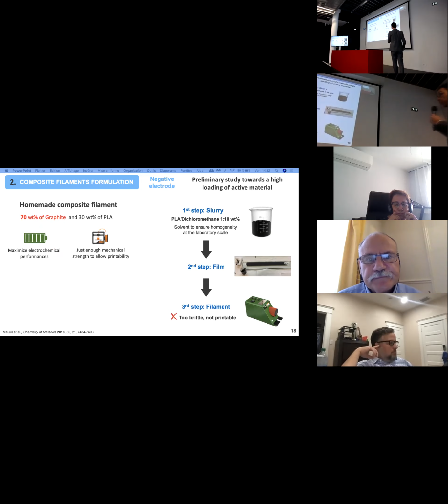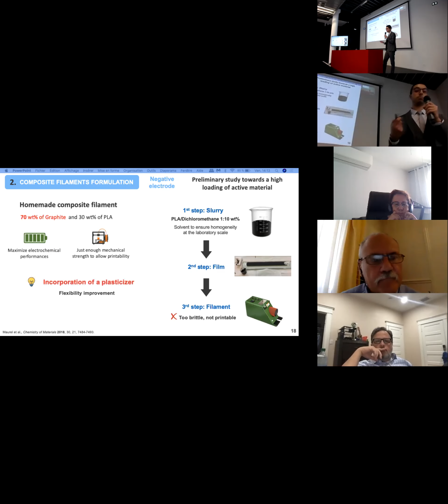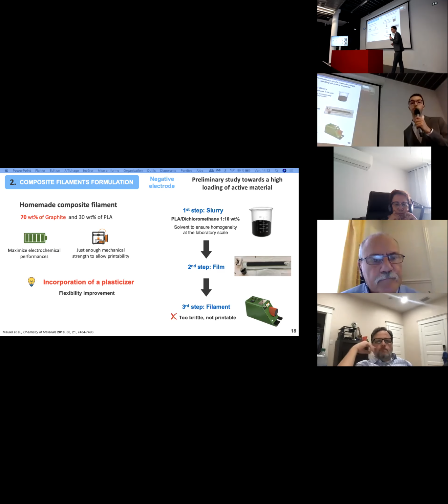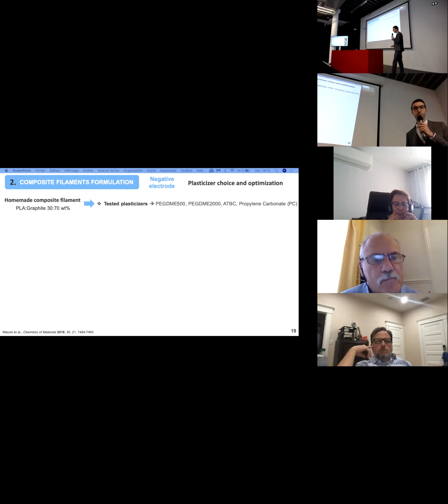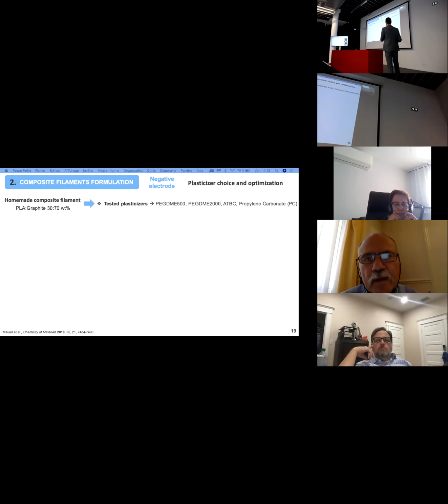It was too brittle. And so we had an idea, and this idea was, why not try to incorporate a plasticizer in order to improve the flexibility of this filament and thus improve the printability. So again, starting from the exact same composition, 30% of PLA and 70% of graphite, we tested different kinds of plasticizer: polyethylene glycol dimethyl ether 500 and 2000, acetyl tributyl citrate, and propylene carbonate.